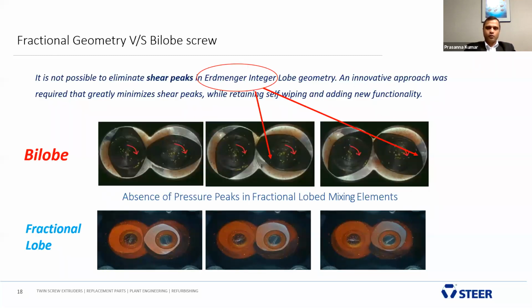To go in depth comparing bilobe technology with fractional lobe technology, we did a study on how the material moves inside a twin screw extruder. As you can see from the picture on the bilobe, the material is getting conveyed from one lobe to the other lobe. And while the material is conveying, you can see a portion of the material here is entrapped and it is not allowed to pass through here.